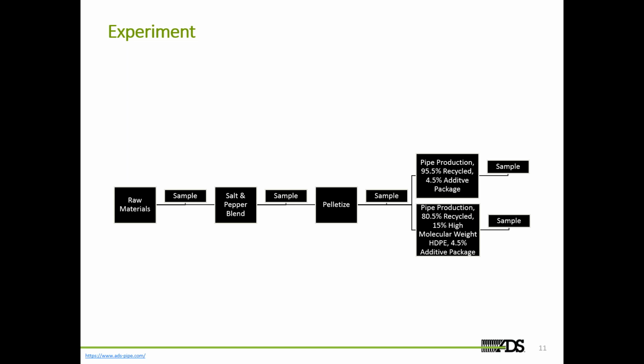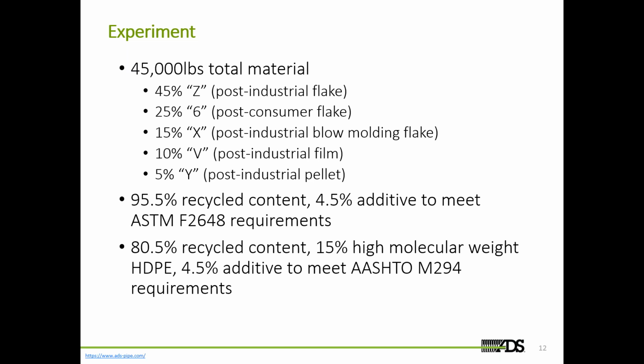So as it runs through a raw material stream, we're taking samples of the raw material, we're salt and pepper blending it, taking another sample, we're pelletizing it, taking another sample, and then we're making it to finish pipe production, and obviously sampling those items as well to make sure that we're hitting the requirements that are needed with the AASHTO specification. The study looked at 45,000 pounds of total material.